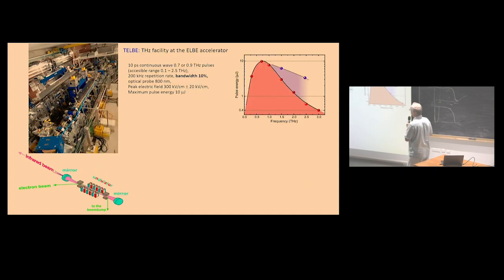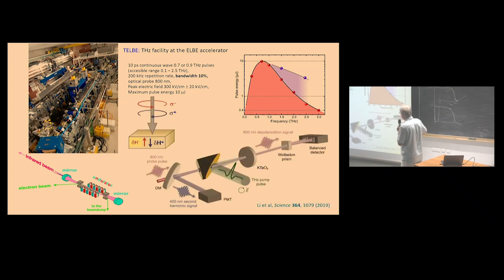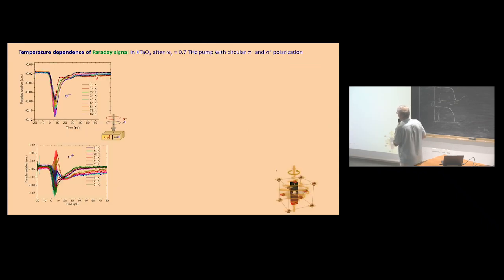And we used the free electron laser in Dresden, which is a large-scale facility, and it has optimal pulse energy around 0.7 terahertz with strongest intensity. So we pumped potassium tantalate and measured rotation of this optical beam, and saw this Faraday effect in transmission mode.